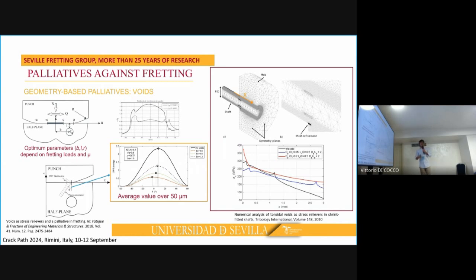Also, we have worked with more industrial application. In this case, we have worked with the press-fitted shaft-hub connection. In this case, we introduce a toroidal void in the shaft. Here, in this plot, we can see the direct stress on the surface, just along this line. And we can see that when compared with the no-void case, and for a certain geometry below the surface, just at the surface, you can observe an important decrease of the direct stress. So it's expected that this type of palliative can work very well.